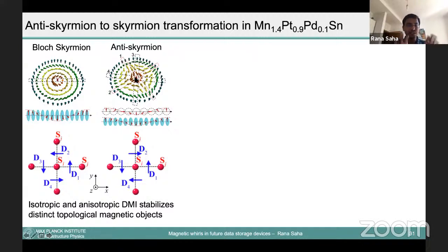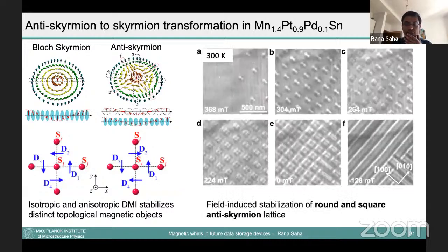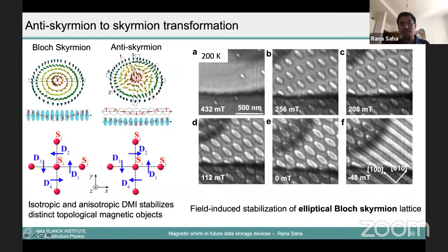So what happens? Remember, this is the skyrmion, this is the antiskyrmion. But remember, these two chiral spin structures are very much symmetry dependent on the material. They cannot coexist in the same material. But what we have observed, this is your antiskyrmion material, and by tuning some kind of magnetic interaction, by playing with the thickness, we can transform from this antiskyrmion to skyrmion. But that skyrmion structure is not the same as this skyrmion. This is some kind of elliptical skyrmion. So in a material, you can have two types of chiral spin textures.